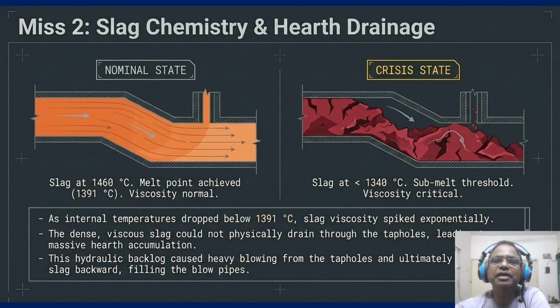So this is the so what factor. The dense viscous slag could not physically drain through the taphole. So this created a hydraulic backlog that caused the heavy blowing. The operator saw that instead of draining out, the slag was pushed backward by the blast pressure, filling the blowpipe. This confirmed that wind casting is often a sign of high viscosity and poor drainage, but it was not just too much wind. The stack was also becoming physically paralyzed by the micro impurities.